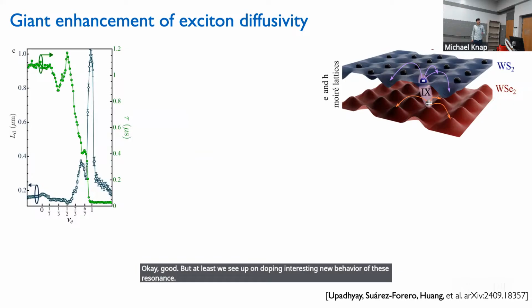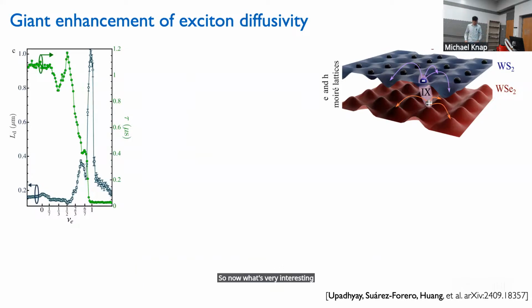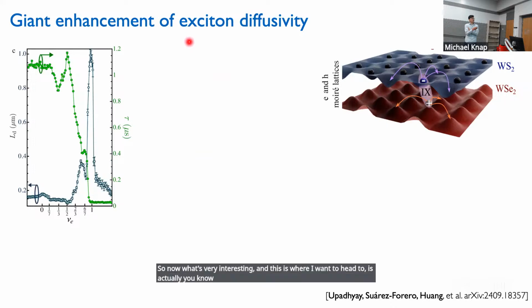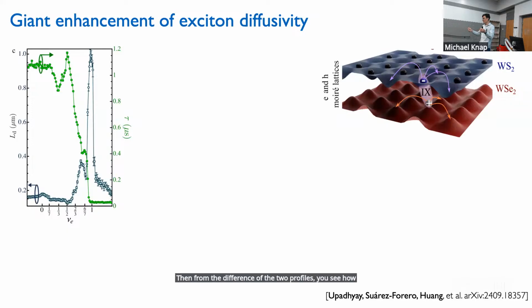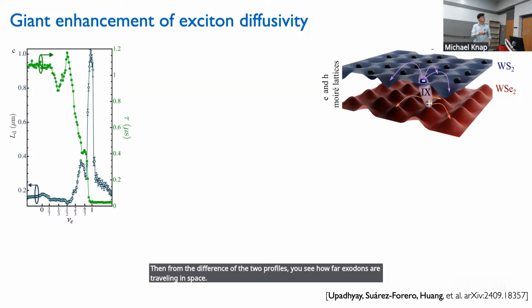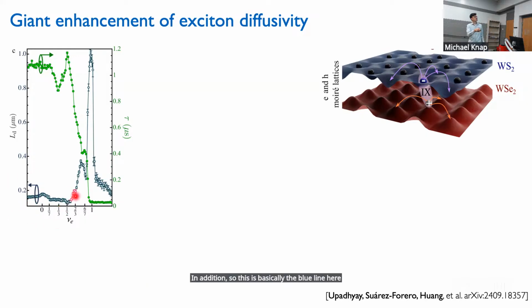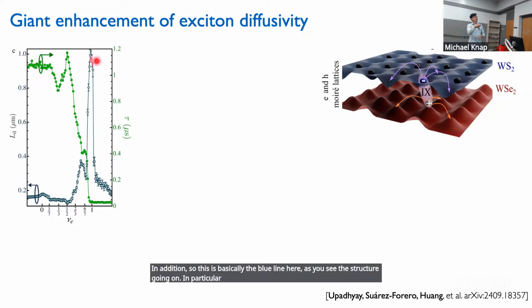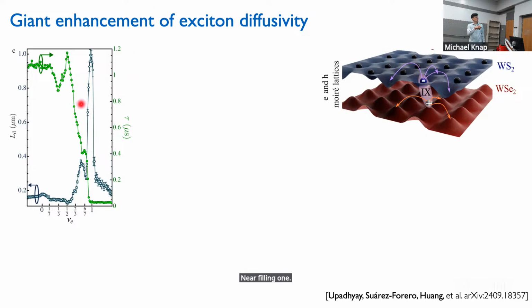Now what's very interesting, and this is where I want to head to: in the experiment, they could measure a length scale of exciton transport. The idea is the following: take a laser with a Gaussian profile, and then collect the light. This will be a new profile. From the difference of the two profiles, you see how far excitons are traveling in space. This is the blue line here. You see the structure going on. In particular, the length scale is gigantic near filling 1. It goes up by roughly an order of magnitude.